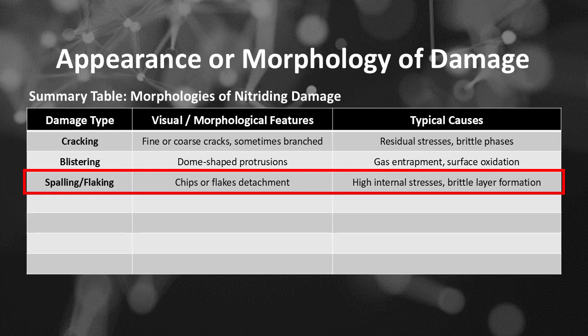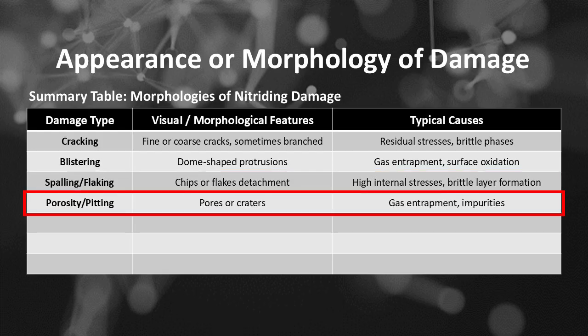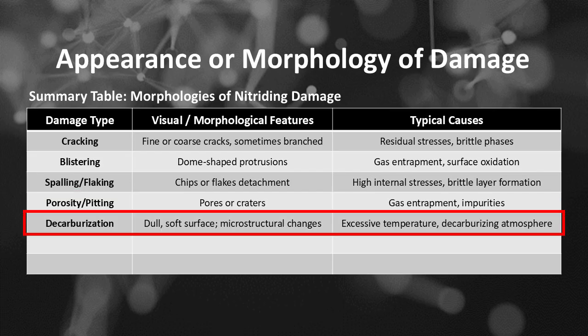For damage type spalling or flaking, the features will be chips or flakes detaching, and the typical causes will be high internal stresses and brittle layer formation. For damage type porosity and pitting, the features will be pores or craters, and the typical causes will be gas entrapment and impurities. For damage type decarburization, the features will be a dull, soft surface and microstructural changes, and the typical causes will be excessive temperature and decarburizing atmosphere.